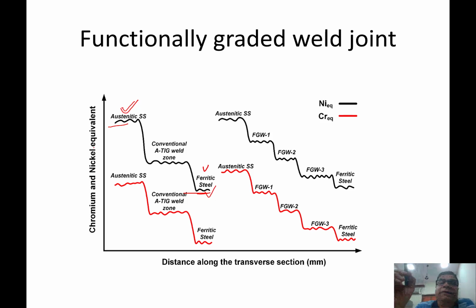So if you see, the black one shows the variation in the nickel equivalent, and the red one shows the chromium equivalent, and such a large difference leads to a lot of variation in terms of the mechanical properties, thermal expansion and contraction behavior, which in turn develops the residual stresses and increased cracking tendency.